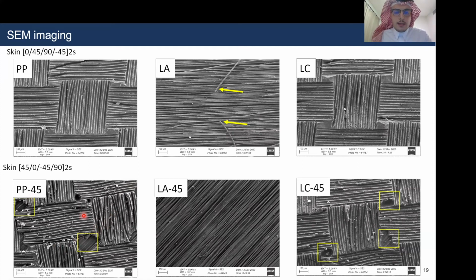A second point to highlight here is that with the LA45, the fibers were not cut. And the difference between the LA and the LA45, why the cutting happened here and did not happen here, is because the laser tip was actually moving in the same direction as the fibers in the 0 direction. So the laser tip was moving in the 0 direction, and the fibers were also in the 0 direction. And this allowed the fibers to accumulate heat and cut. While in the 45 degrees, the laser was moving in the 0 direction, and the 45-degree fibers were able to cool down by the time the laser came back again.